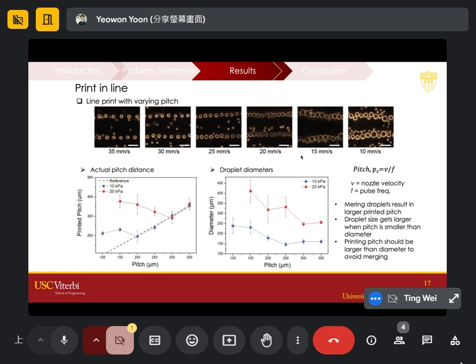The second study we did is to figure out how closely we can put droplets together. Is there any critical distance we shouldn't go below? The first top figure shows different speeds, and different speed means different distance between 2 droplets. If you move slowly, you have a shorter distance between the droplets. And what happened when droplets were put closer together is they ended up merging into one bigger droplet. For printing, this is like an artifact. So we wanted to find out the critical distance at which we can put droplets together.